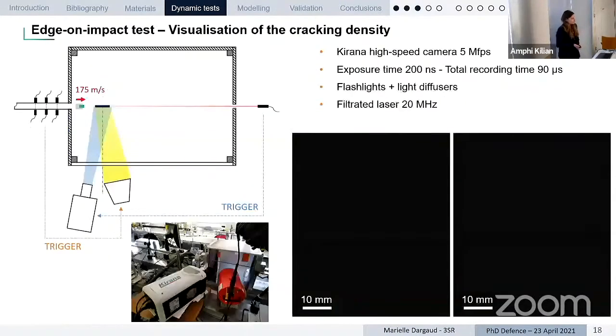Then we've performed the dynamic test. Here you have images for the edge-on impact test, with a scheme, a top view of the configuration. We've used a mirror-polished surface for the ceramic to be able to visualize the fragmentation in the tile upon impact. For this, we are using an ultra high-speed camera with a frame rate of about 5 million frames per second, and we are using a flashlight because the event is going to be extremely quick.